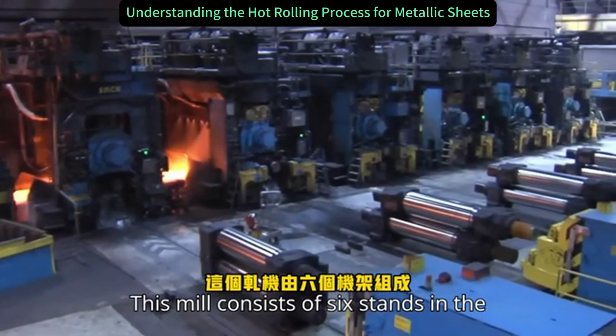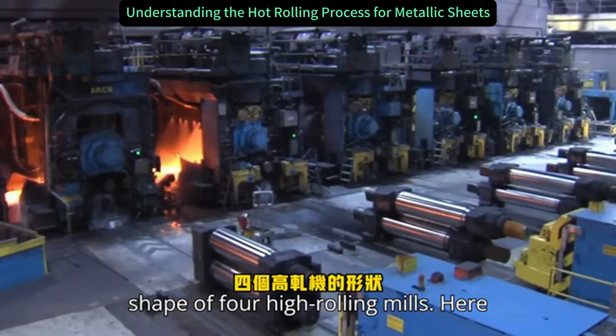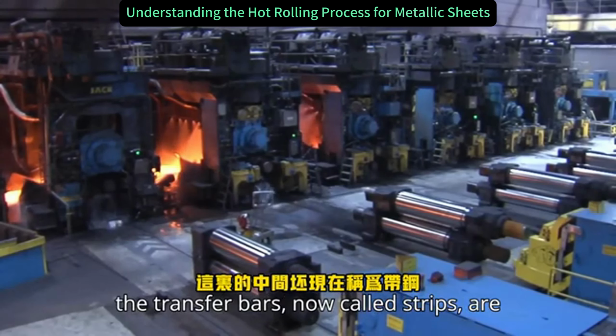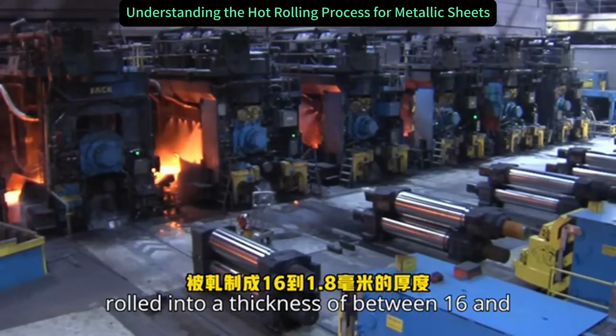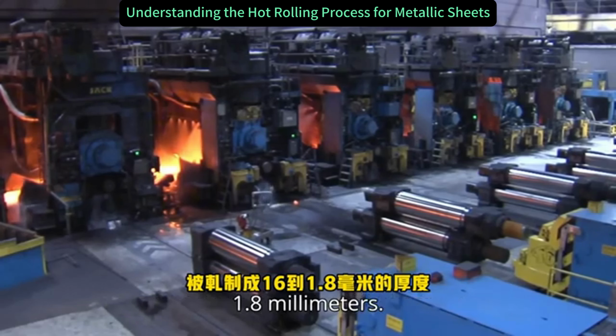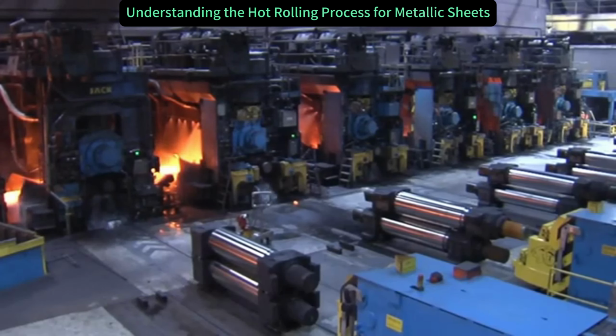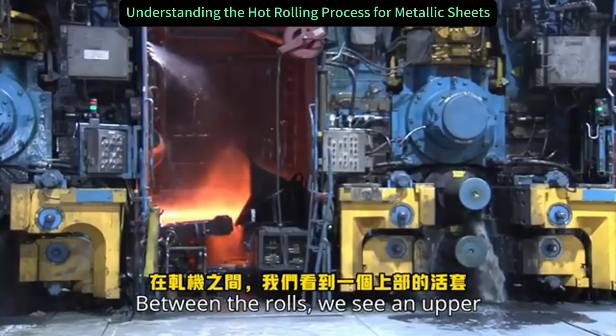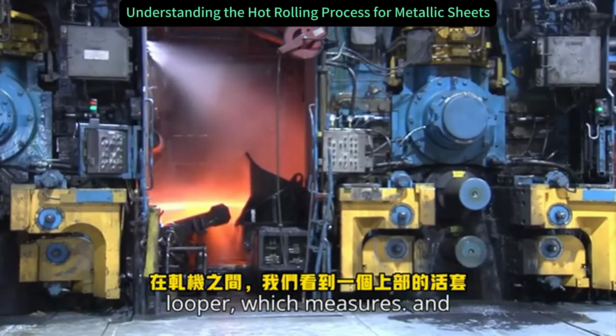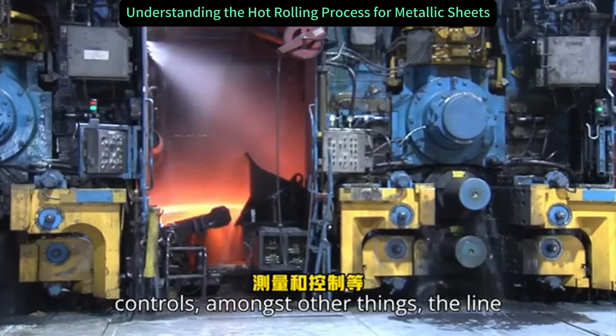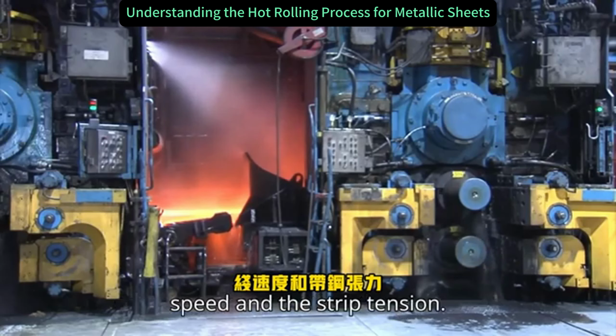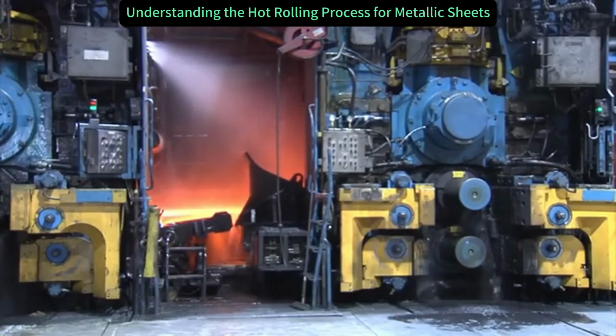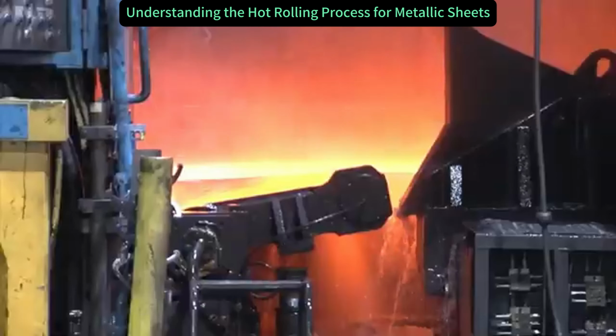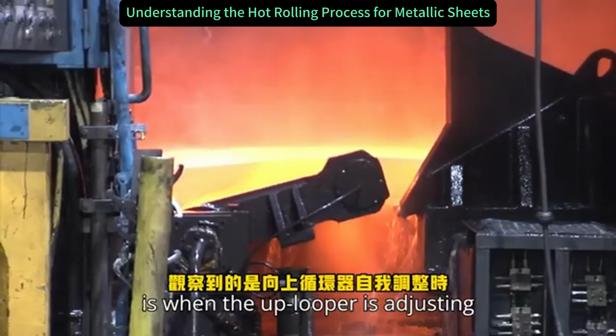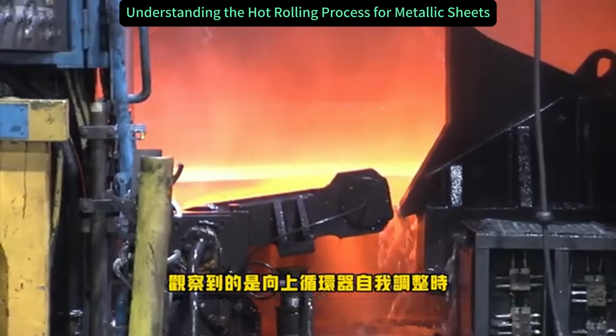This mill consists of 6 stands in the shape of 4-high rolling mills. Here the transfer bars, now called strips, are rolled to a thickness of between 16 and 1.8 millimeters. Between the rolls, we see a looper, which measures and controls, amongst other things, the line's speed and the strip tension. The swinging motion that can be observed is when the looper is adjusting itself.